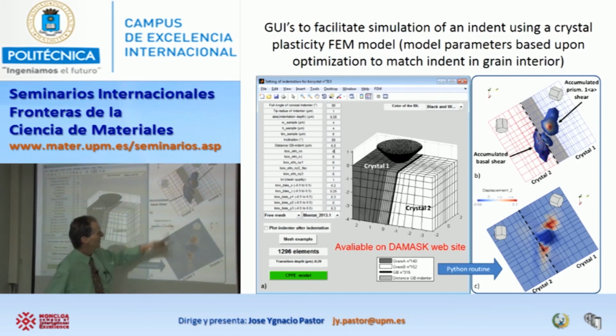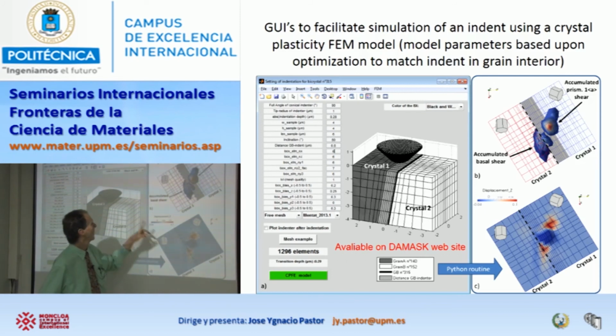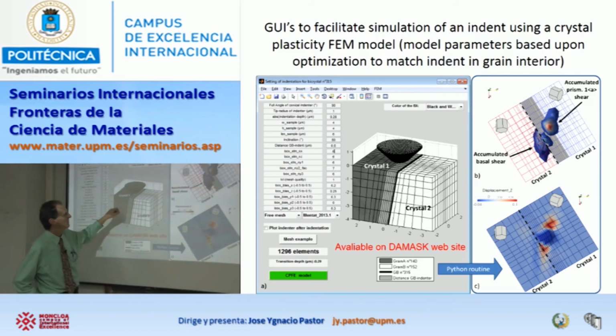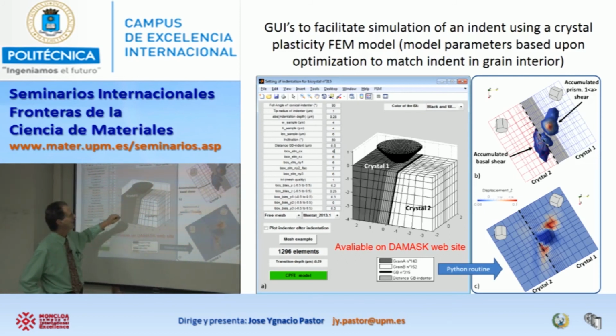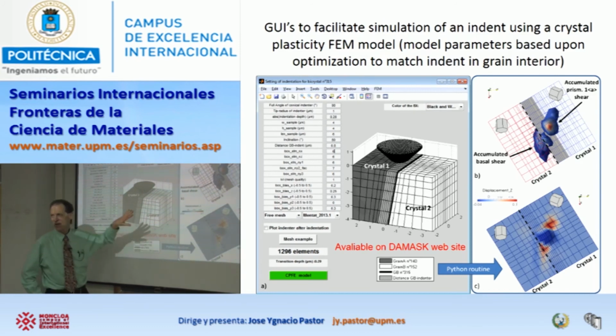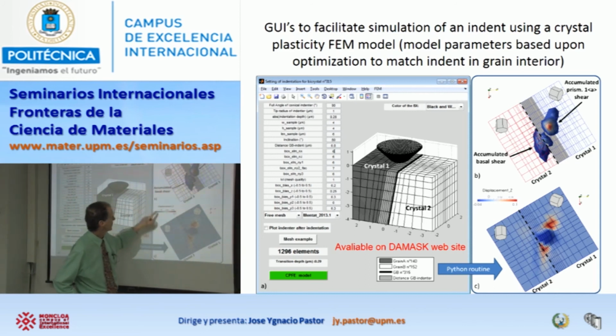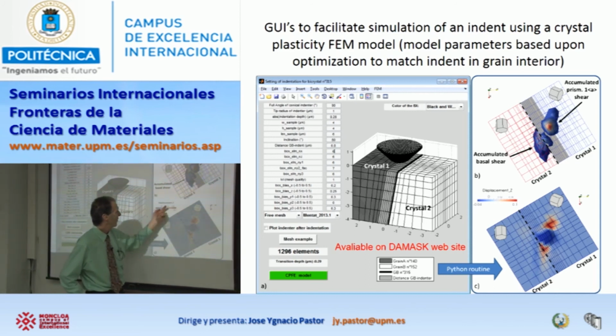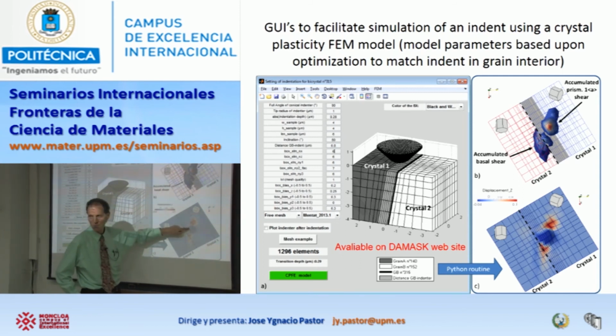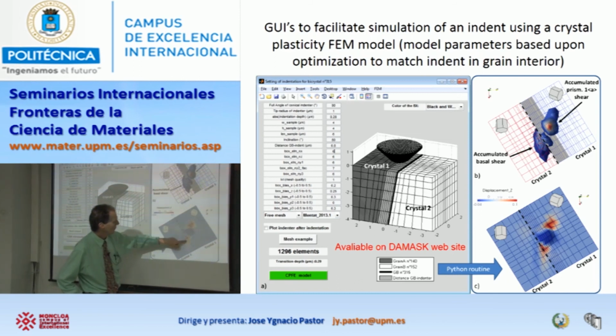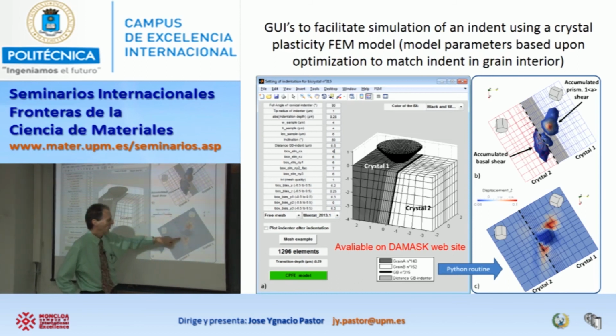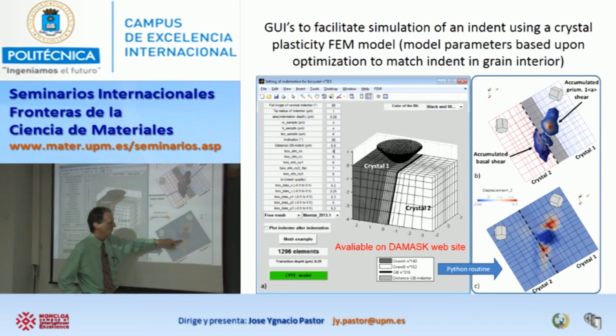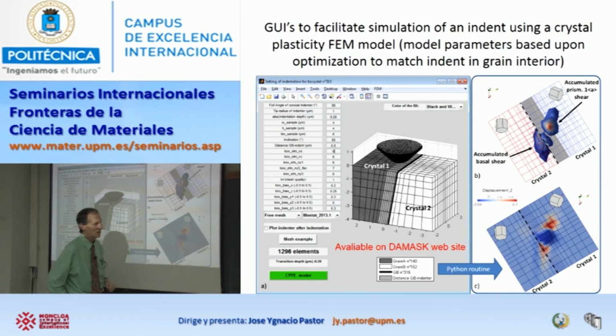And we can make a simulation of this as well, with a computational code. But we can also measure the topography using AFM and get the actual geometrical height. So this is displacement in the Z direction, coming out towards you is red, going in, which is where the indent is, blue. And so can we predict the shape change that's occurring when essentially one side of the indent is right on a grain boundary?